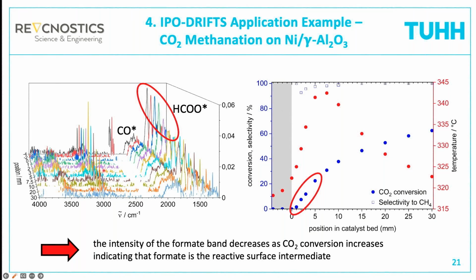And another problem is we have only one drift cell, only one crucible. So after we are done with the catalyst measurements, we have to open the drift cell, exchange the catalyst by the pure diluent, and start the whole measurement again. And between the measurement on the catalyst and the measurement on the calcium fluoride, at one and the same point, we have about 12 hours of difference. And in this time, there might be drifts in the spectrometer, there might be drifts in the reactor, there might be drifts in the catalyst, and this will lead then to inconsistencies in the correction.